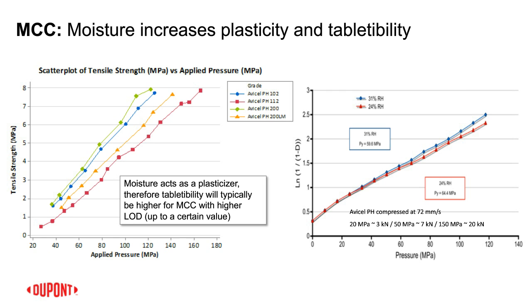The moisture upper limit is 5%, but typically you're going to see between 3 to 4%. And for Avicel PH 112, the upper limit is 1.5%. So a lot of times you're going to see right below 1%. So that's the difference. It really gives you a better starting point, especially for a moisture sensitive API, right? You're looking for an excipient with a lower moisture content to minimize the interaction. Yeah, I see. Thanks.